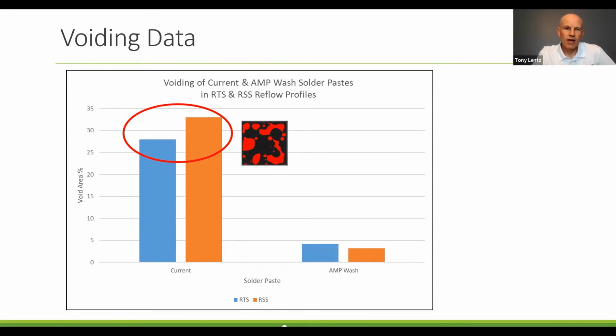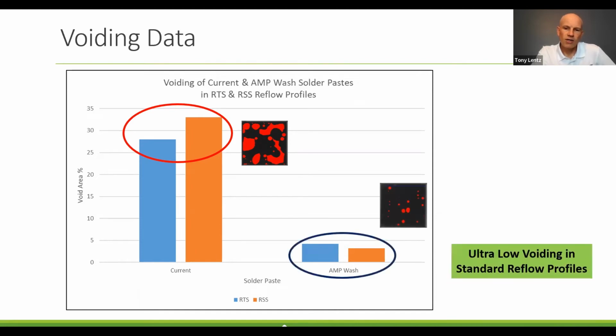And that's pretty high. That void area is beyond normally accepted limits for most of our customers, which 25 is a pretty widely accepted number on these types of components. Sometimes we hear about lower numbers as low as say 15 or 10% void area. Well, the current technology, water soluble lead-free pastes are usually not able to handle that. Whereas Amp Wash gives you voiding down below 5% void area on the same test board with those same QFN components. So we're considering that to be an ultra low voiding solder paste.